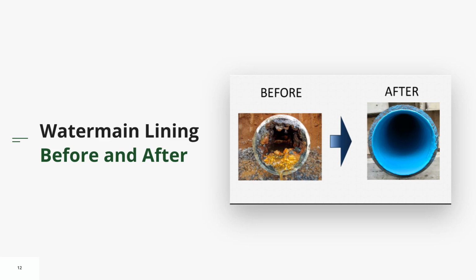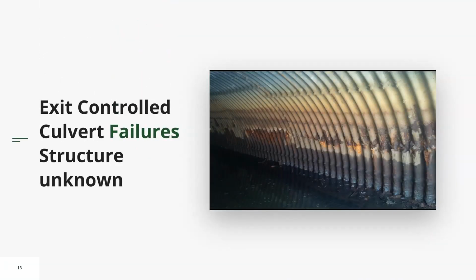Out of water pipes and down into a corrugated steel structure, culvert. So we're talking now about a much bigger pipe. This was a pipe in the city of Richmond, just under Highway 99, which becomes the I-5 in the US. This pipe had failed on the right-hand side, and this is what's called an exit control culvert, which means that there is standing water in the pipe all the time. Therefore, the invert of the pipe in this case is probably in pristine condition. The obvert of the pipe, as you can see in the top of the photograph here, is in great shape.